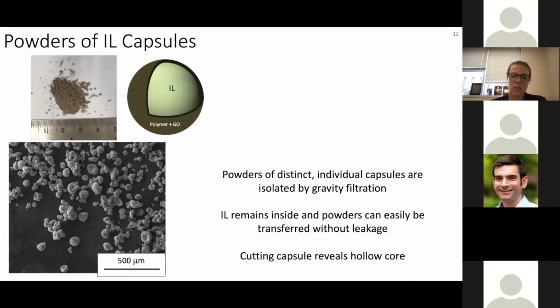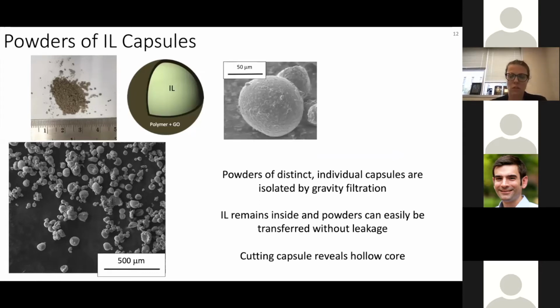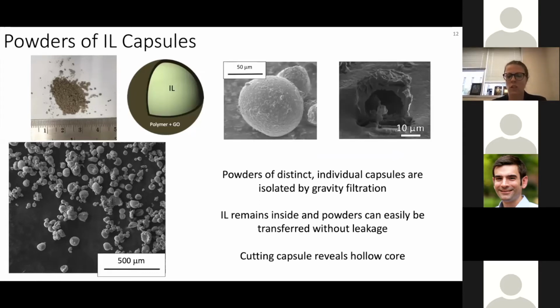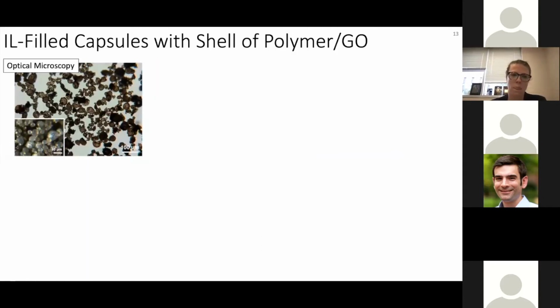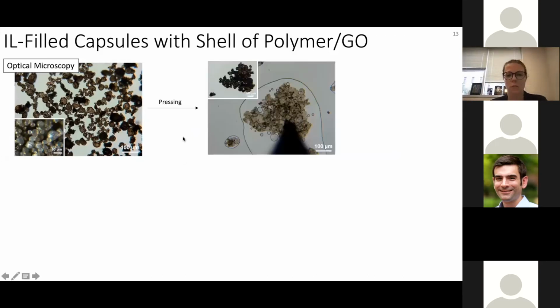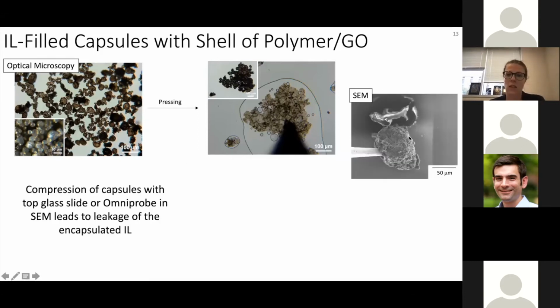From SEM, we see we do have individual particles. They have this rough surface morphology. And then if we cut the particle with the FIB, we end up seeing the core shell type structure here where the ionic liquid has come out after we cut the system, after we cut the capsule. We can also take the capsules on optical microscopy and press a glass slide on top, and we see the ionic liquid does come out. We can do this in the SEM.